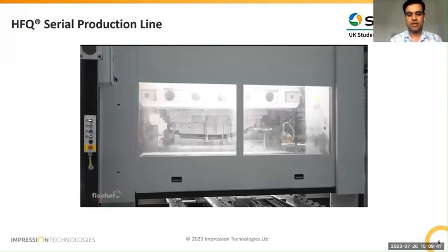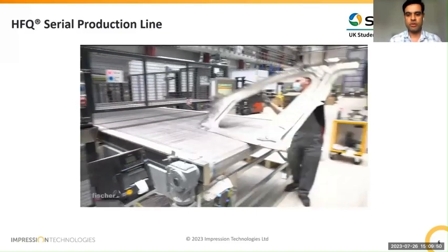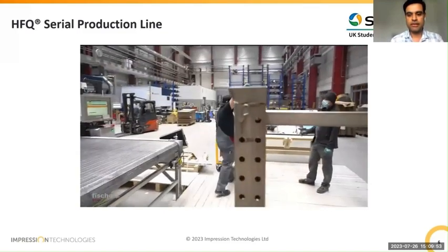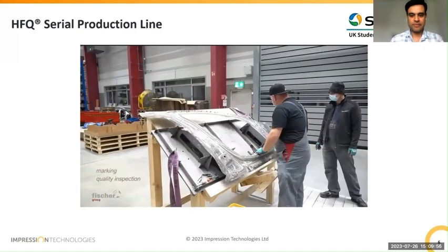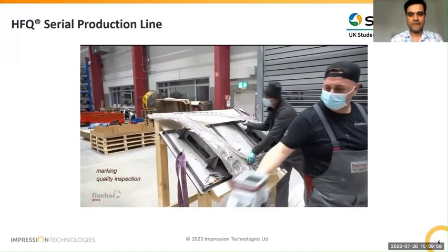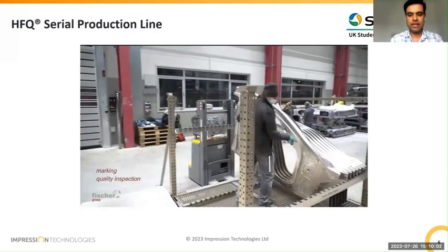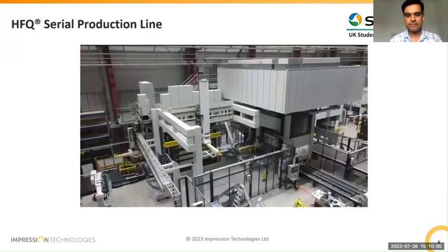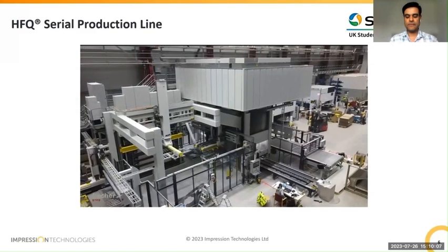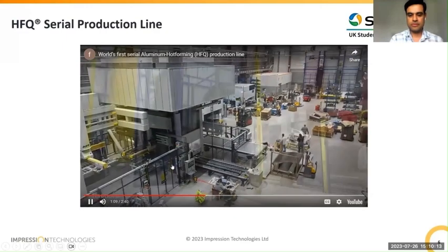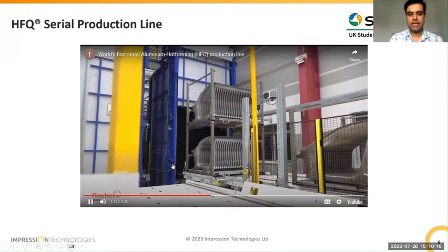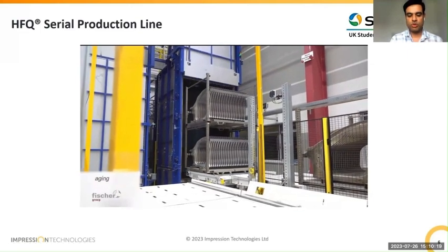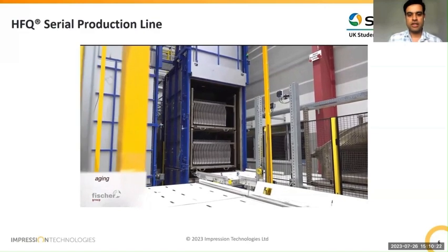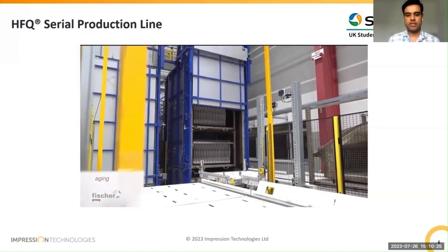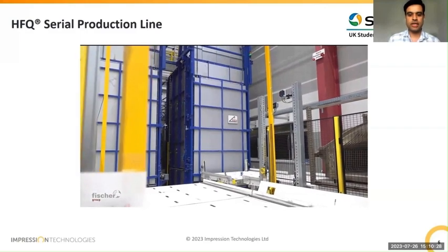And after the quench time, it's removed from the press, visually inspected. And then it's stacked. That goes on for cleaning. Once it gets into the aging, where it gets the final property, so it's moving inside an aging oven. So that's the advantage of HFQ, is you can tailor the final properties of the part depending on where it sits and what the mechanical property requirements are.